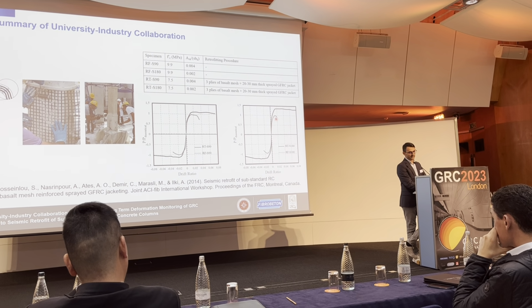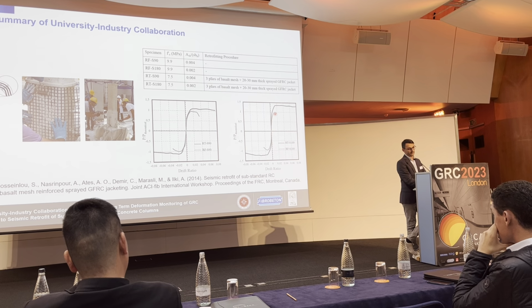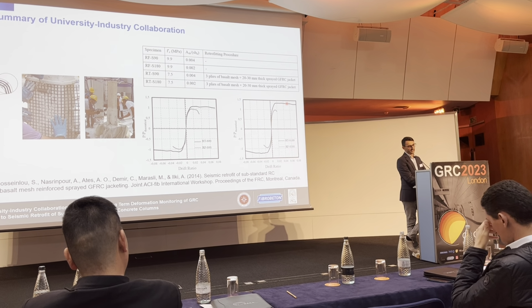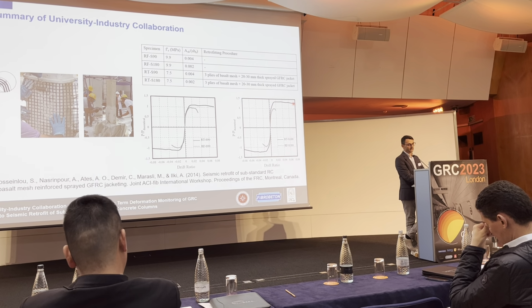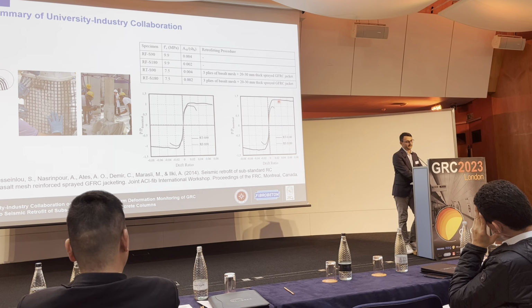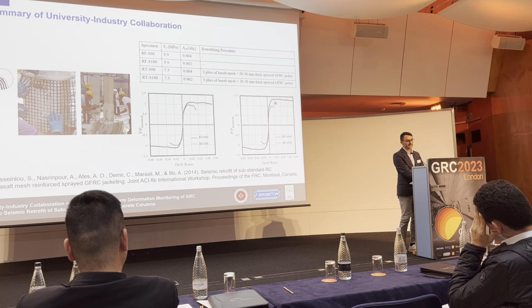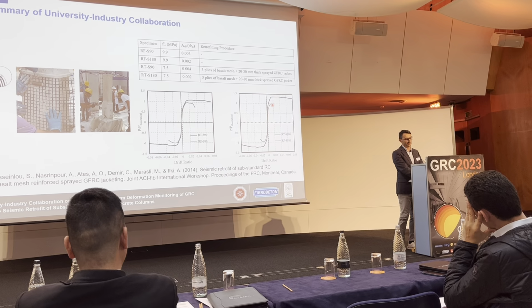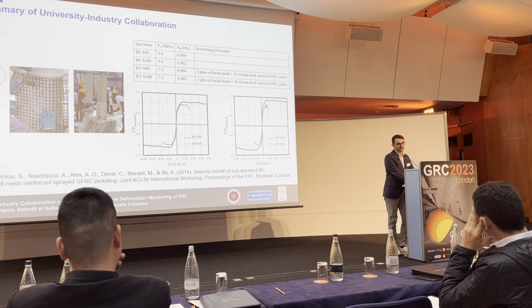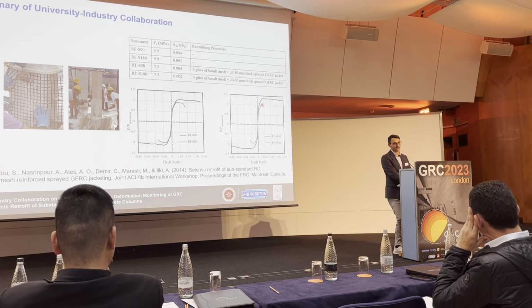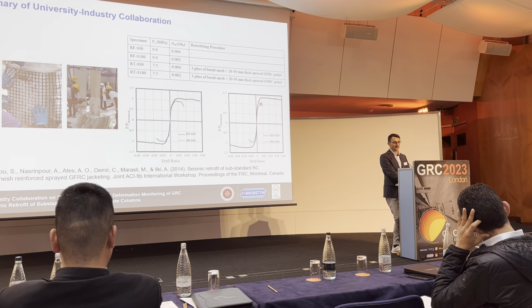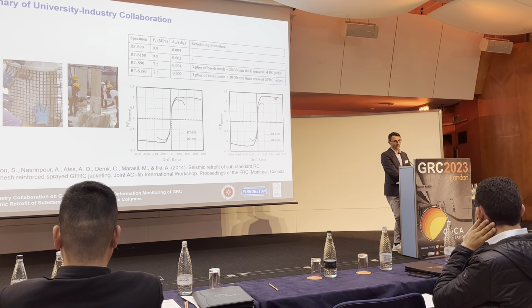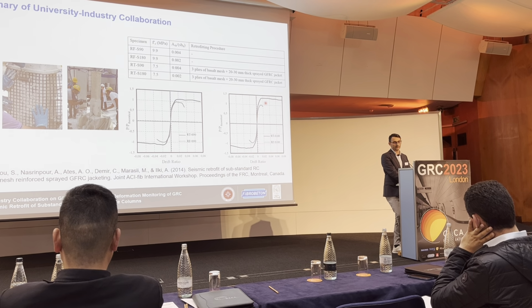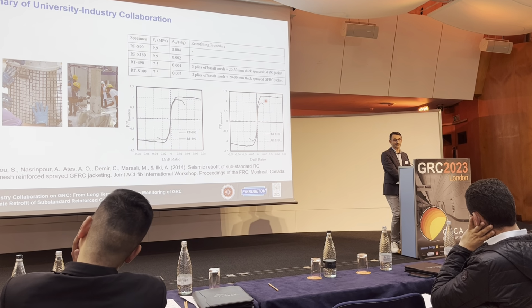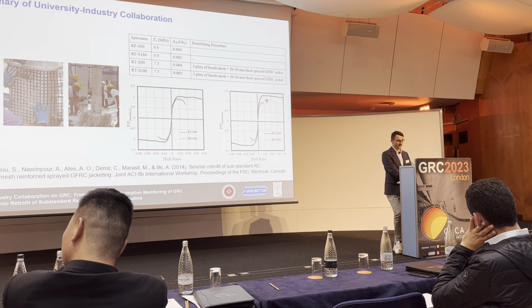And here, this is the reference specimen, which means that it is unconfined, unjacketed, and this is the case where we have jacketed the specimen using 3 plies of basalt mesh and then spray GFRC. As you can see, this vertical difference corresponds to the contribution of the retrofitting method in terms of lateral load bearing capacity. And this horizontal difference refers to the ductility enhancement that we gained using this spray GFRC.